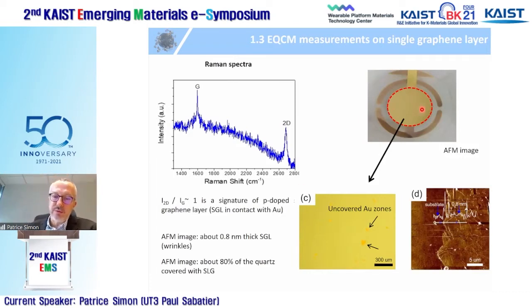We took a gold quartz and we deposited, as I mentioned, a single graphene layer, SGL. And then what you see here, optical observation, you have some slight uncoated and covered gold quartz zones, but it's very minor. About 80% of the gold quartz is coated. Raman spectra is typical for, I would say, a p-doped graphene. And then you have some wrinkles, but this is very minor on the electrode.